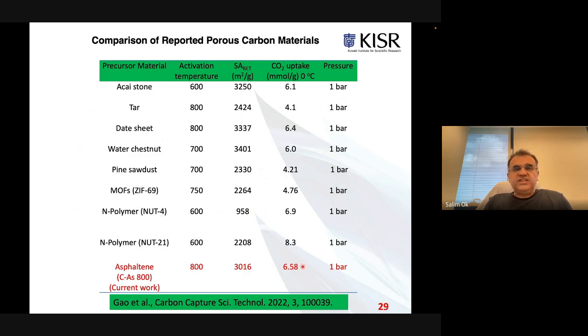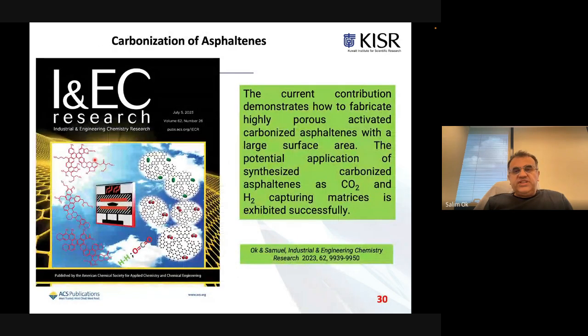On the other hand, when it comes to carbon dioxide uptake in terms of millimole per gram at 0 degrees Celsius, again our values are pretty promising and closer to the commercial polymers, and seriously higher than the other carbonized materials coming from natural resources. Again, we were pretty happy. It took us slightly a year to get our work published in the case of carbonized asphaltenes.